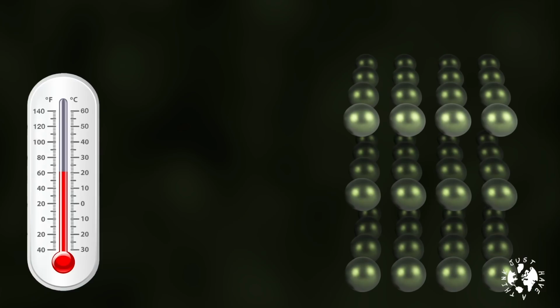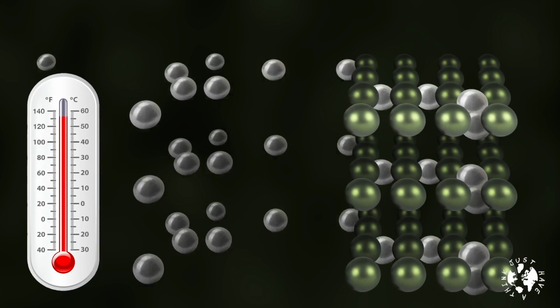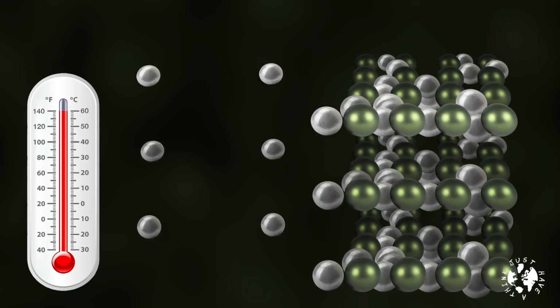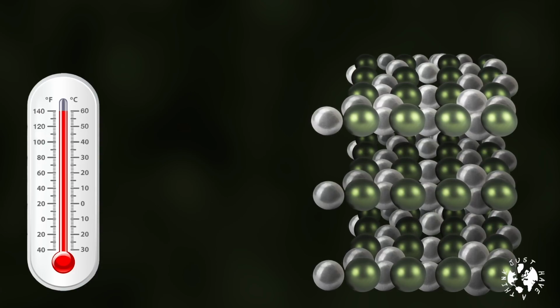But the team at Penn State University seem to have developed an effective way to minimize this lithium plating that extreme fast charging causes by actually increasing the temperature at which the charging takes place. The researchers found that upping the heat from 20 degrees Celsius to 60 degrees Celsius can increase the lithium graphite interweaving thing by about 13 times, and more interweaving, or intercalation to use the proper sciencey word, means less lithium plating.